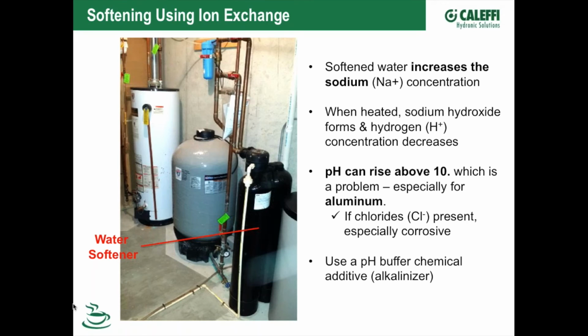Resulting in the pH can rise. In fact, it can rise above 10. And that might not be a problem for many systems. However, if your system has aluminum, aluminum doesn't like to have typically a pH anything higher than 8.5, to that earlier point. So the bottom line here is that if you have aluminum in your system, it could be a fan coil. A lot of fan coils will have their coils made out of aluminum and other parts, or an air handler, or a boiler, or some aluminum boilers, right?